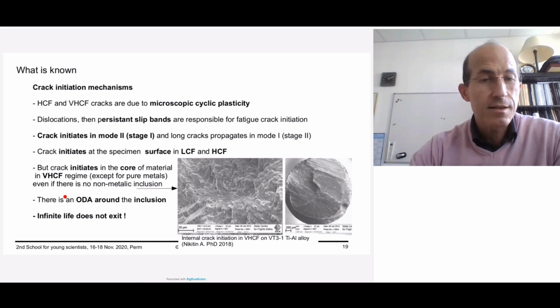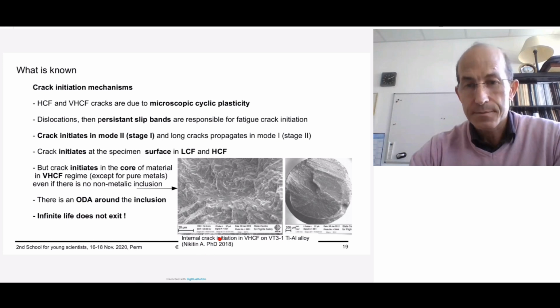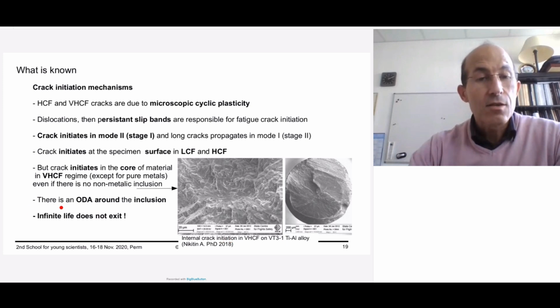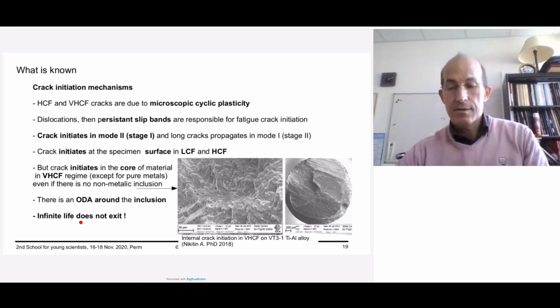But the same thing is observed even if there are no non-metallic inclusions. You can see here an illustration on a titanium alloy in the PhD thesis of Alexander Nikitin. And in this alloy, this is characteristic, the crack initiation appears without any inclusion. You can see here a typical fish eye, but no inclusion in the middle of the fish eye. On metallic alloys, especially steel or ferrous alloys, an optical dark area surrounds the inclusion, and of course, no infinite life exists.